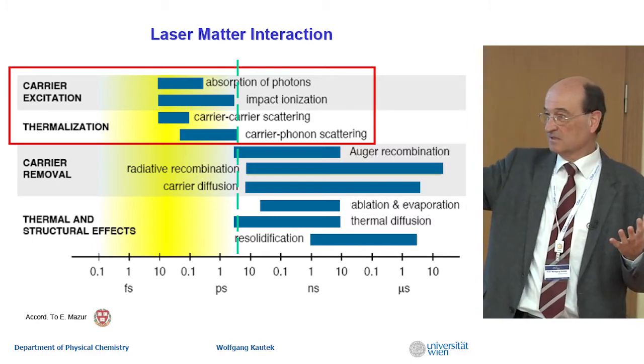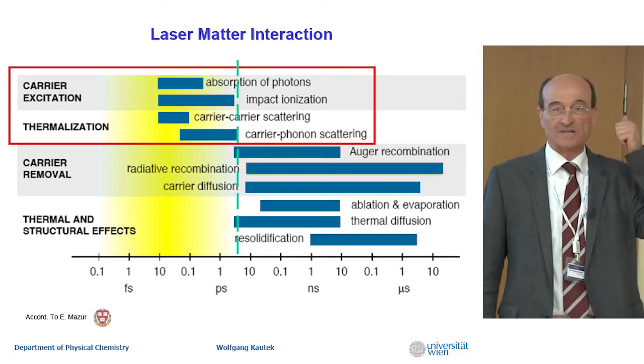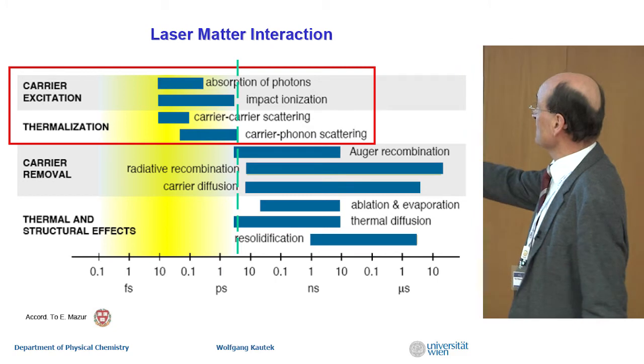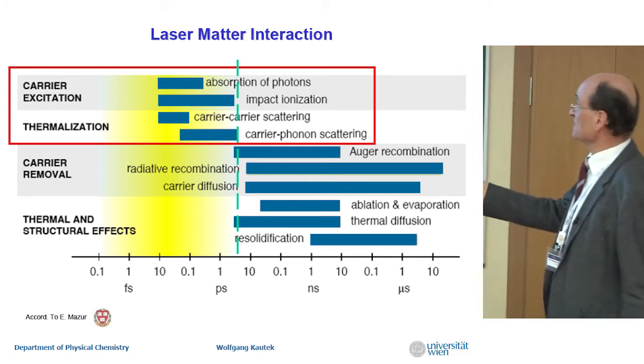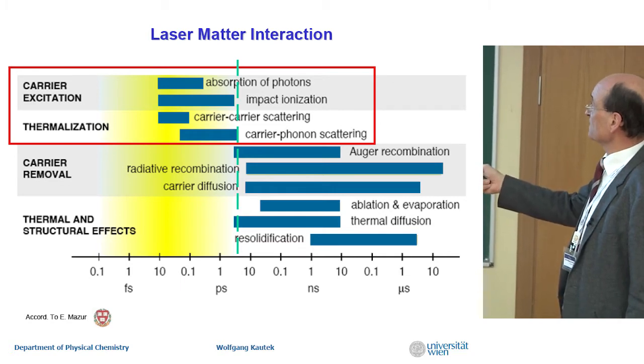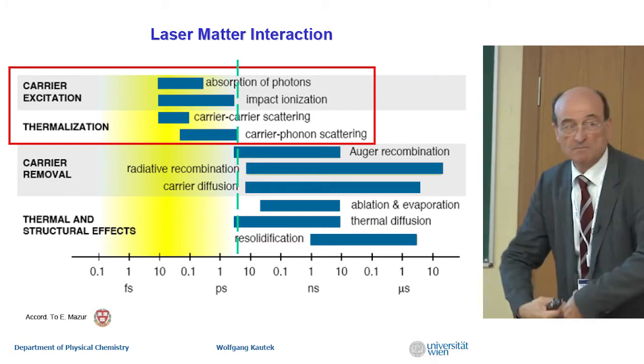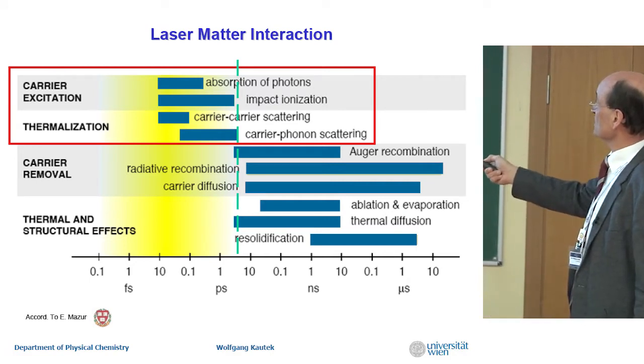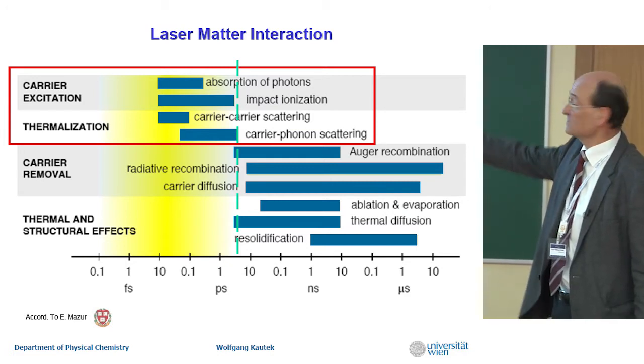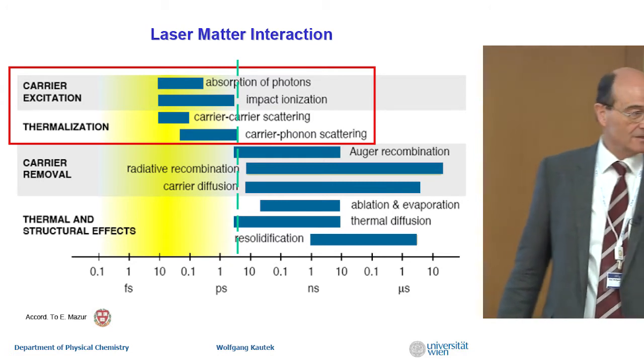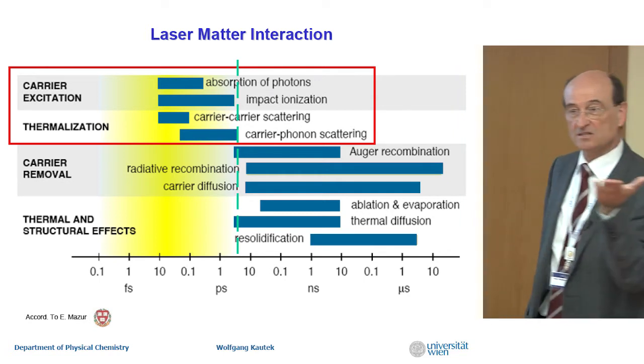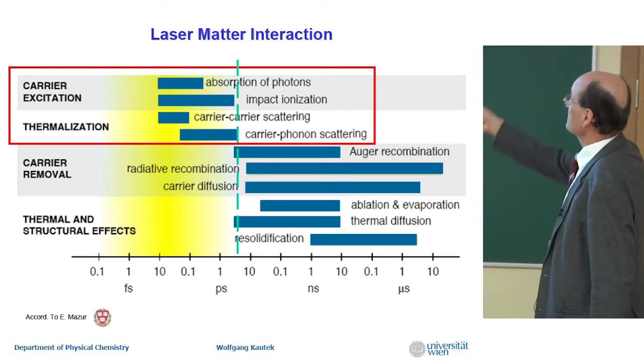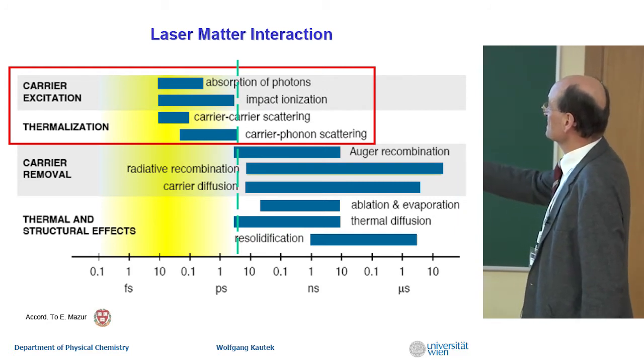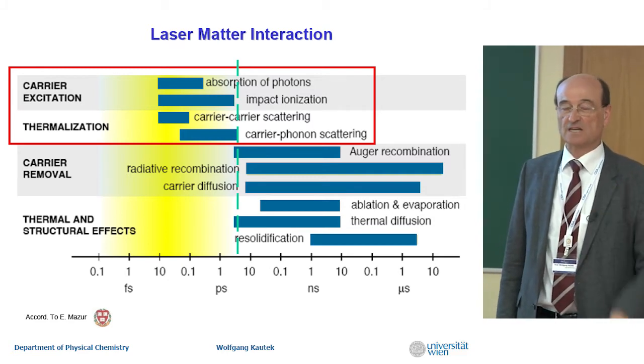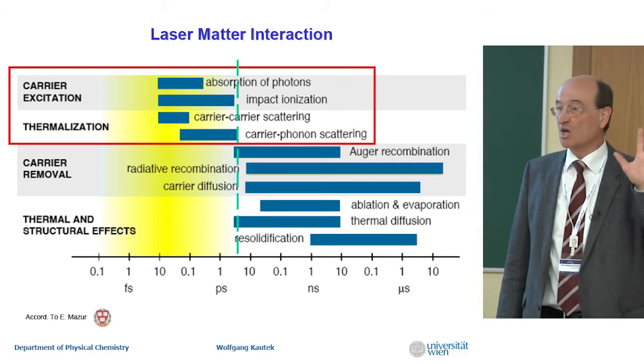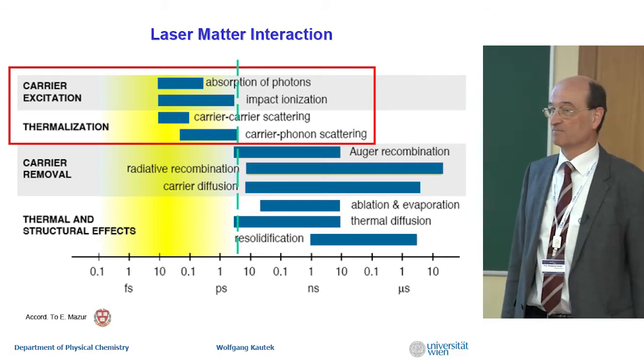The electrons are hot, the lattice is cold, the lattice doesn't know that there are hot electrons yet. Okay? Afterwards, you have a bunch of processes, quite complicated: the carrier removal, Auger, radiative recombination, carrier diffusion, and then material move, ablation, evaporation, thermal diffusion, and that's the end of the story, and that's what the engineer needs, the resolidification product. That's how the workpiece looks like. So that's the border between the non-thermal and the thermal processes. It's a couple of picoseconds. Therefore, if you want to use that domain, you have to pulse shorter than 10 picoseconds or 1 picosecond. Good.